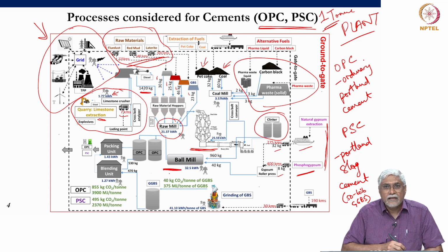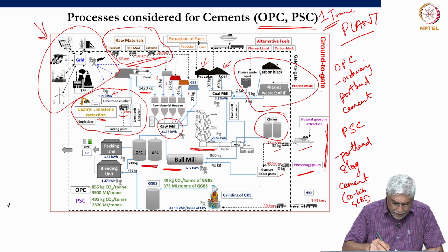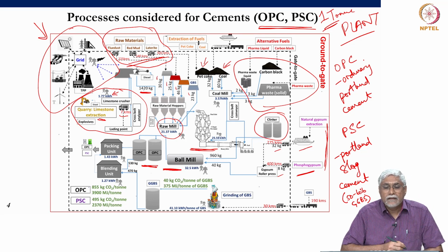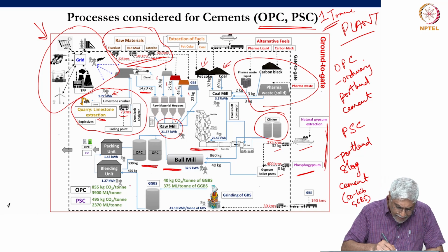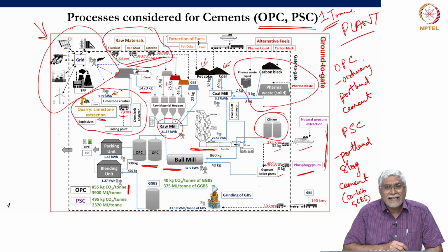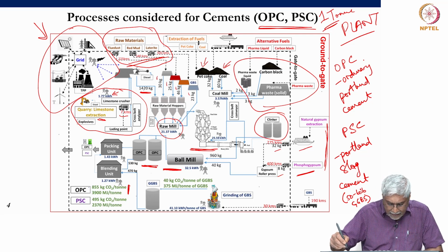is ground along with the clinker, and the product is ordinary Portland cement, which is packed and sent out of the plant after blending with certain performance enhancers. About 5% can be blended into the ordinary Portland cement before it comes out as a marketable product. So, in this case, the values come out to be about 855 kilograms of CO2 per ton of cement is the carbon footprint, and this is for the analysis of gate to gate.